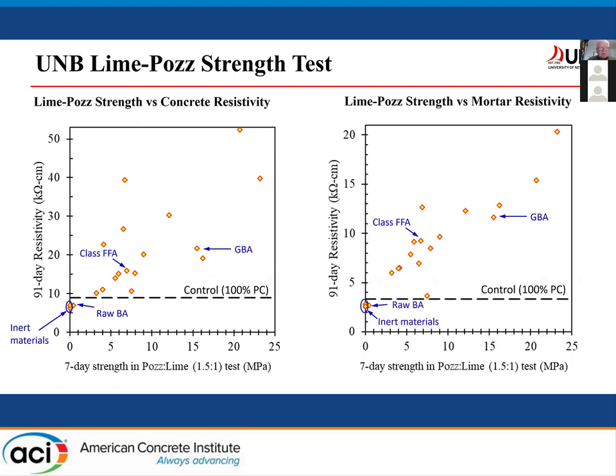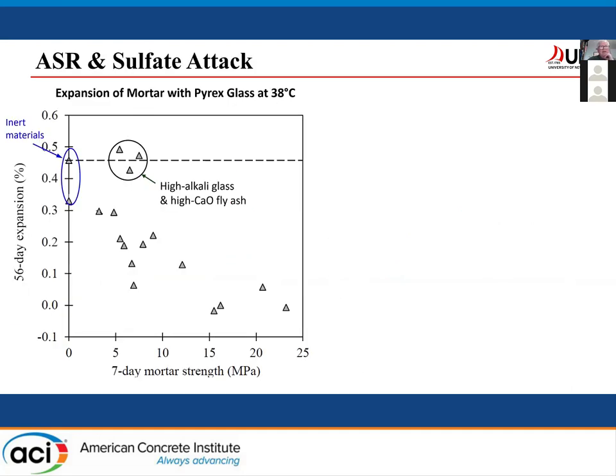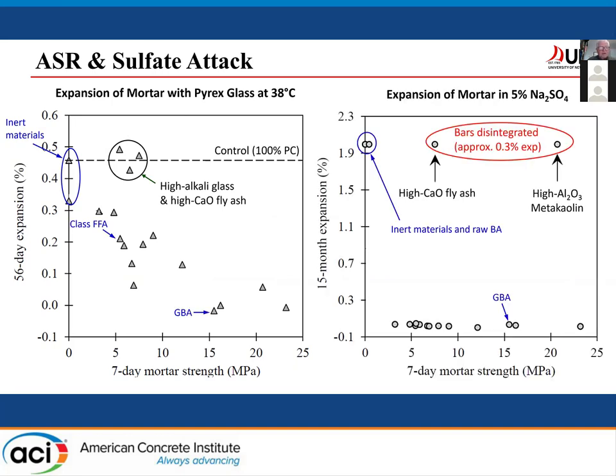The ground bottom ash is shown here again. Higher resistivity relates to better strength in the test in both cases here. Okay, this is the Pyrex mortar bar test showing the ground bottom ash again, very low, zero expansion, and it relates to the higher strength in this proposed test method. And again, the ground bottom ash performed well over 15 months in ASTM C1012. Very little expansion, next to zero.